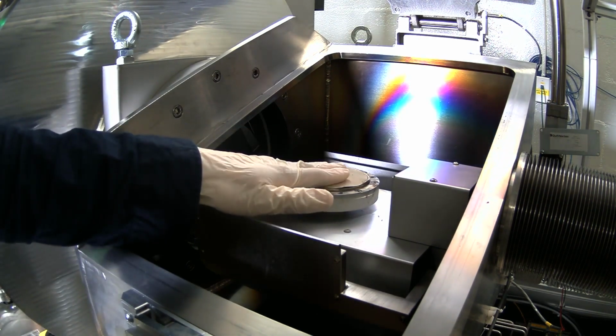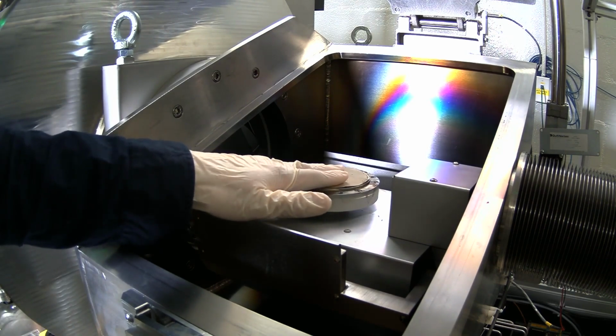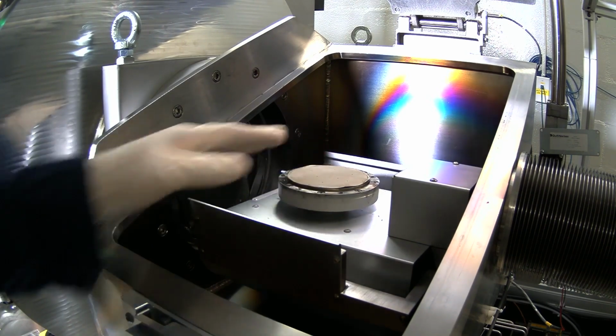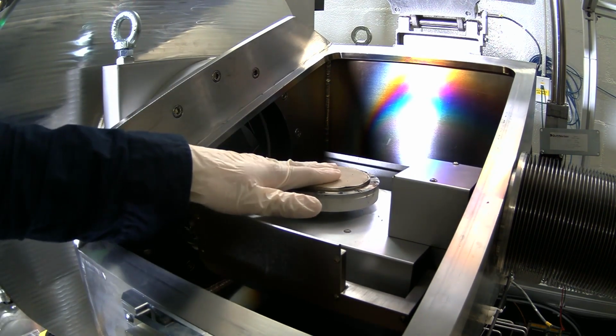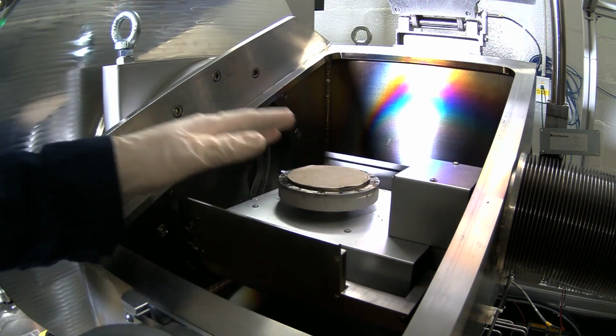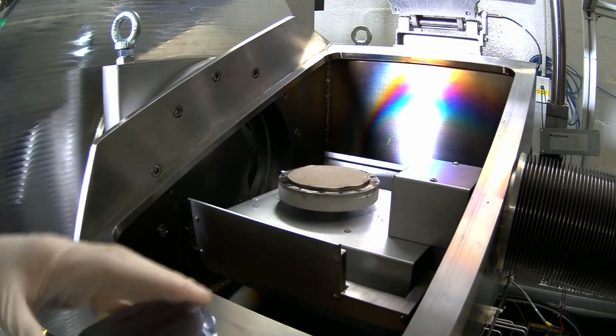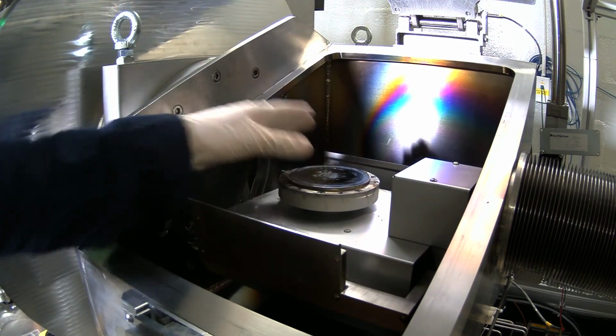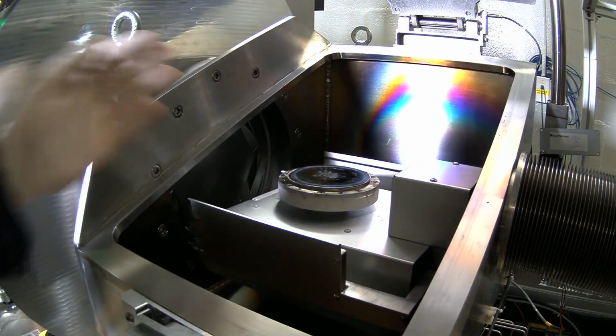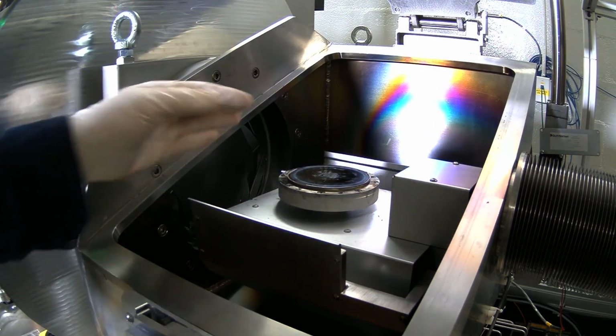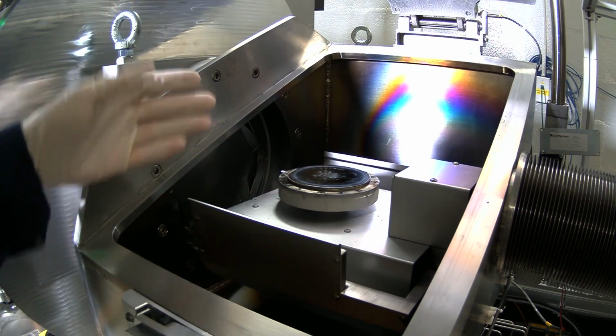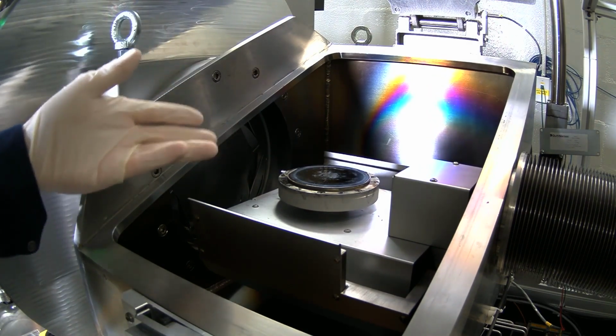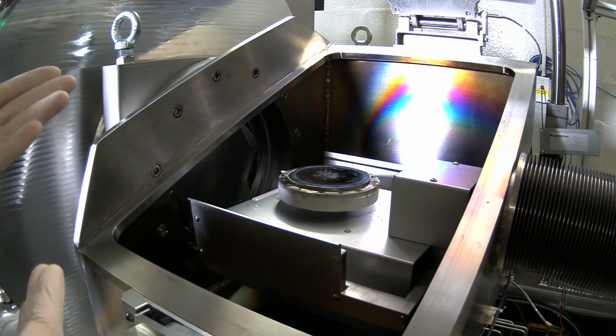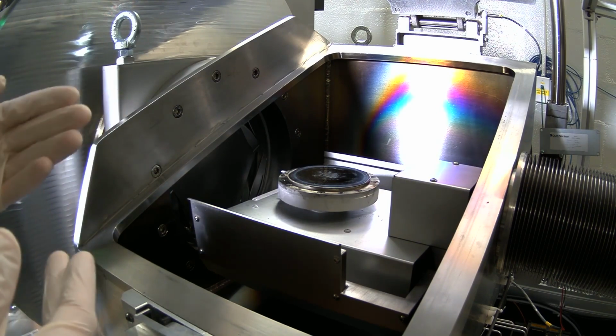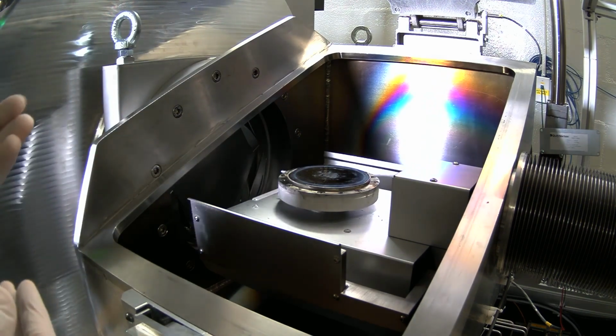The piece that I'm putting down first is a thermal pad, because we want good thermal conduction between the device and the chuck. So that goes down first. Then this piece of silicon wafer, just a test grade silicon wafer, protects the chuck from etching. We want to use silicon here because it has low sputter yield and it's not going to produce a bunch of elements that are going to confuse the SIMS.